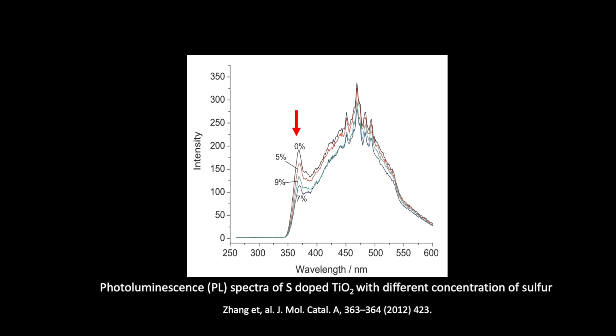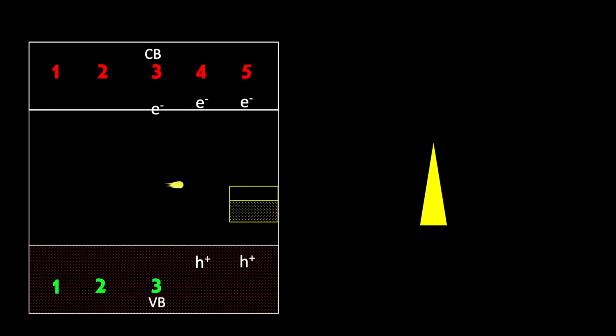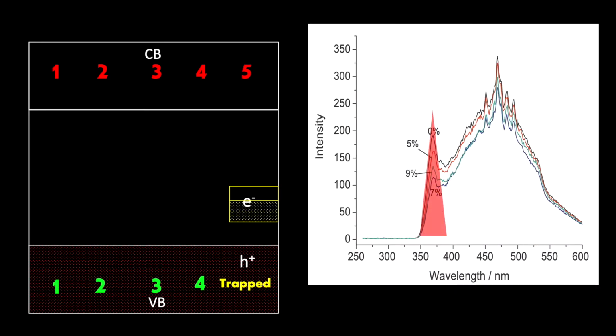reaction. Most of the experimental evidence for electron trapping behavior in sulfur-doped titanium dioxide is based on the lower intensity of the first relaxation peak in the photoluminescence spectrum. This peak is due to recombination of electron-hole pairs and electron entrapment could result in lower intensity. This reduction in the intensity has a correlation with sulfur content. But there is a concern here.